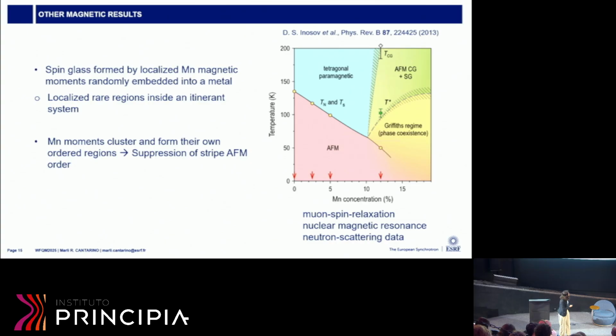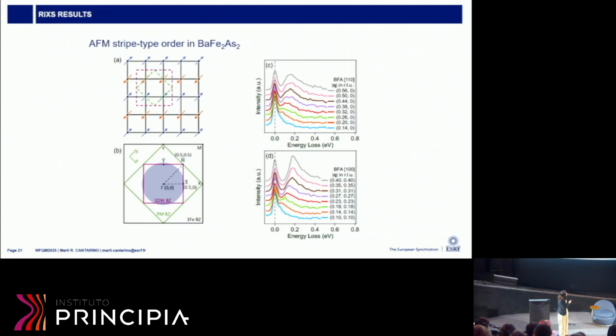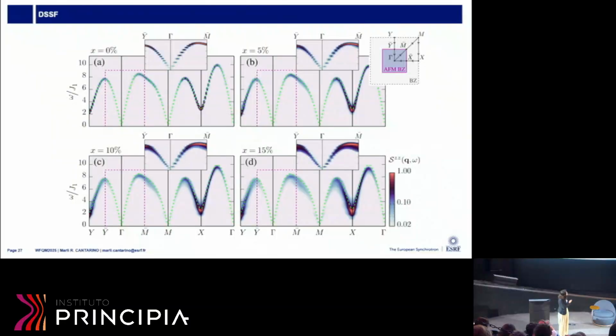No, because when you look at the color maps, what you see is the spectral weight being transferred to lower energies—that's what I call damping, so the peaks are getting broader. That's one effect, and on top of that there's also another effect of bringing the spectral weight to a different Q point. So they're not the same thing, but they both happen with doping. Maybe they are related, I don't know.